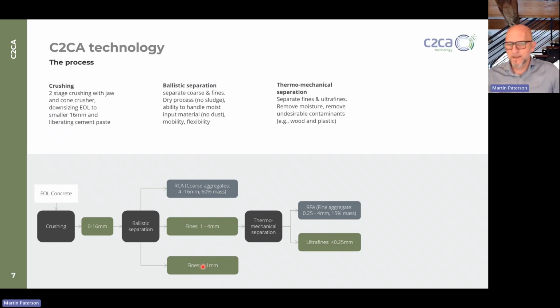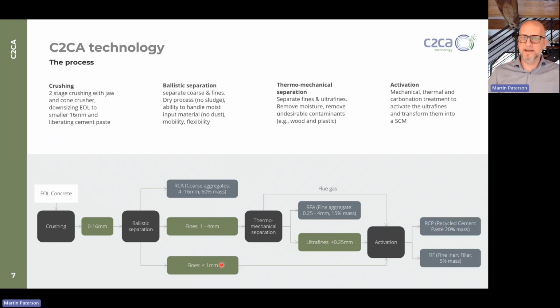Many companies, I think, are doing some kind of recycling of waste concrete nowadays. They do it in a dry process, semi-dry process. Some do it with chemicals. And up to here, I think the performance might be better or lower, but it's not too different. What is really different is that we take these fines and we now activate them. And the activation, I will also show in a detailed slide later how it works. But in principle, we downsize the fines further. We grind them down to a D50 of 10 microns.